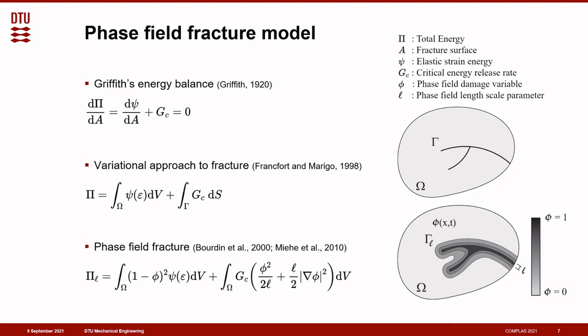First, by looking at the first integral, you can see how the phase field parameter affects the stiffness of the solid through a degradation function, and therefore acting similar to continuum damage models. And from the second integral, you can see that there is a gradient term and consequently a length scale. So the model is non-local, which ensures mesh objectivity. So basically, results are mesh insensitive as long as this length scale parameter is resolved.